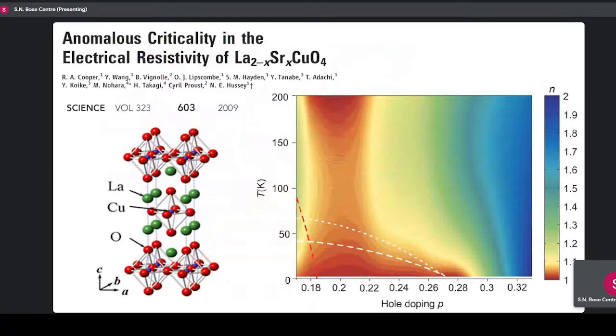So in particular, here's a famous plot of the resistivity. What's been plotted here as a function of hole doping and temperature is the resistivity exponent n. You just take the logarithmic derivative of the resistivity with respect to temperature, and n equal to 2 is the Fermi liquid value, which you see at rather high doping. But when you get to the interesting regime, where the superconductivity in this case has been suppressed by a magnetic field, you see an exponent closer to 1 over this funnel-like shape.